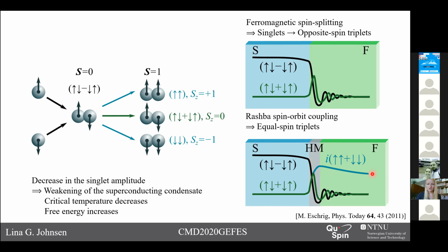What we instead do in our system is that we have only one homogeneous ferromagnet, but we introduce Rashba spin-orbit coupling through the heavy metal layer. And in this way, we can create equal spin triplets, and the amplitude is dependent on the direction of the ferromagnet in a similar way as in the system where we had two ferromagnets, but we can manage with just one ferromagnet.